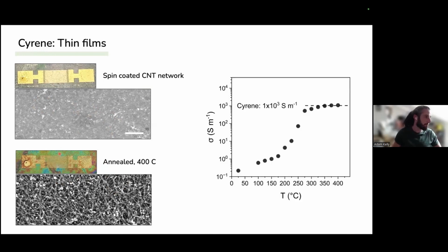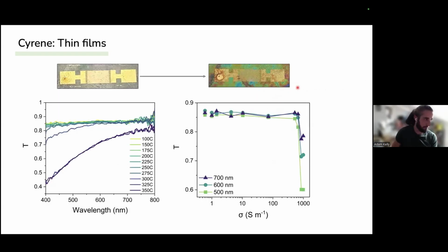So as for the conductivity, we measured it as the temperature goes up. It begins quite low because there's clearly quite a lot of solvent still trapped in here between the nanotubes. And then as all the solvent boils off, we reach a plateau at about 1,000 Siemens per meter. As a control, we also created some carbon nanotubes in IPA. We spin coated these onto these same electrodes, and because it's IPA, it evaporates off fairly quickly. And at room temperature, you can achieve conductivities that are about a factor of 10 higher.